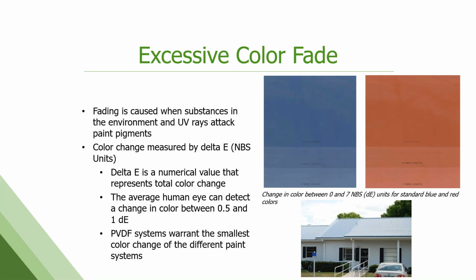Excessive color fade is a big one, right? No one wants a building that's going to fade quickly. They want it to look the same for many, many years. Fade, of course, is due to UV exposure, fading the pigments. It's measured numerically by a value called delta E. We can actually go out and measure the change on these buildings from beginning to end. The human eye starts to pick up color difference at about a 0.5 to a 1 delta E unit change.